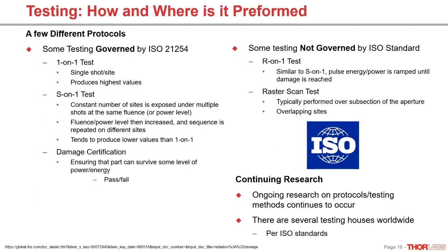So as far as testing, there are a number of different protocols. Many of them are governed by this particular ISO standard, which you are certainly welcome to read and familiarize yourself with. These include the one-on-one test, which is exactly what it sounds like. It's one laser damage shot per site, and this tends to produce the highest values. Unfortunately, at least in any setup I've worked in, we want to use more than one shot per laser. So one-on-one is typically not the best method to look at, but it's available.